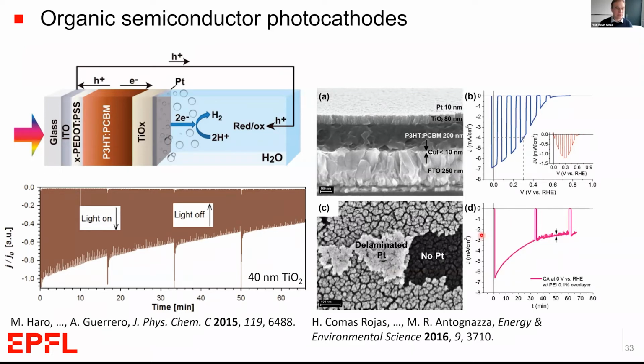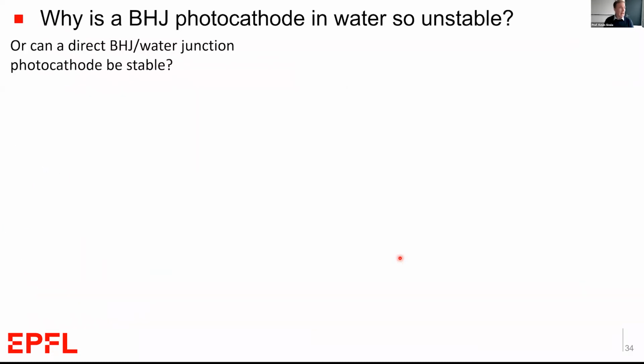Now, the authors in this case have attributed the drop in performance to delamination of the platinum on the surface. And I think that is an important aspect that still needs to be addressed. But I think a more fundamental question is, can organic semiconductors, especially these bulk heterojunctions, be stable under these photocatalytic or photoelectrochemical conditions? And that's a fundamental question that we wanted to answer in our group.